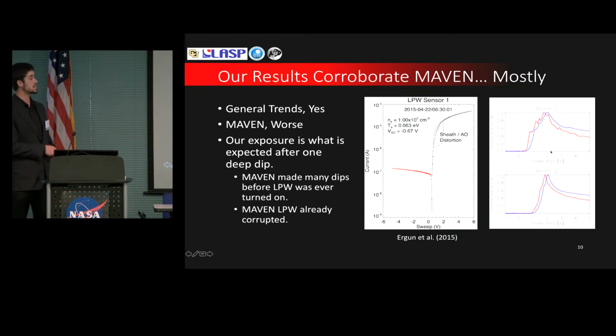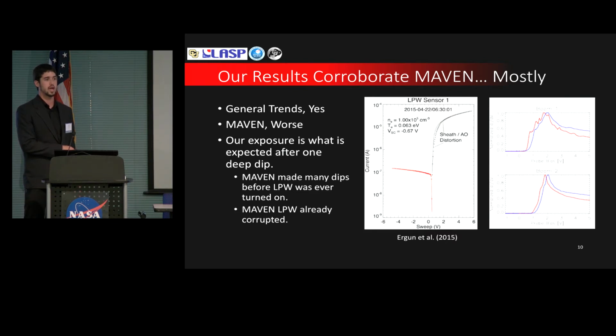To put that into context, our 20 minutes in our chamber corresponded to 1.5 dips into the Martian atmosphere. So if MAVEN was flying for months, making a dip into the Martian atmosphere roughly every 4 hours, then the titanium nitride probe was about as degraded as possible.